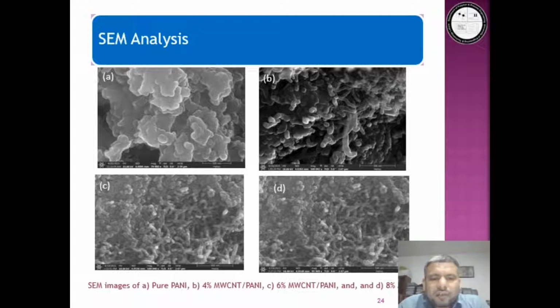However, agglomerates of CNTs can be observed at higher CNT contents of 6%, 8 weight%, as you can see in figures C and D. The agglomerate formation degrades the continuous morphology as well as the adhesion between the components of the nanocomposites. The low adhesion and disjointed path resist the flow of electrons and thus result in poor conductivity of the composites.